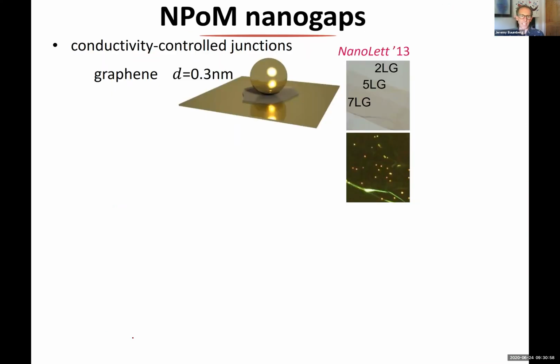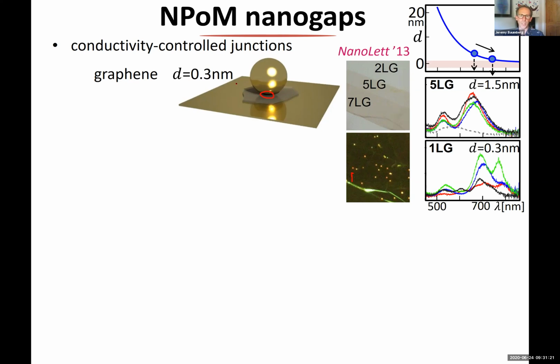So I'll show you just a little bit of what we did originally. We looked at these graphene samples. You can make graphene of different thicknesses. It doesn't really matter what graphene you use, because the graphene in the gap here is just a very small amount of the total graphene. So even if you use CVD grown graphene, it always looks perfect under the nanoparticle. And you can see already that there are different colors here. And these different colors you can just measure by scattering spectroscopy. So you send light in at some high angle and you look at a different angle. So most of the light, of course, bounces against the flat gold, and you don't look at that. You look at the light in dark field here, which is scattered to a different angle. And that light has gone into this mode that's in the gap here.